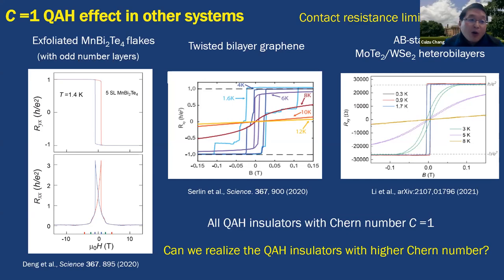In all these systems, in my opinion, it's pretty difficult to realize the room temperature quantum anomalous Hall effect, because no matter whether in ferromagnetic or twisted systems, we need the ferromagnetic Curie temperature to be around room temperature. That's pretty difficult. For example, in the magnetically doped topological insulator, if you want to increase the magnetic doping level, as I just introduced in my talk, it usually drives the magnetically doped topological insulator trivial. You will lose the quantum anomalous Hall state if you increase the magnetic doping level. In my opinion, if you want to realize a high temperature quantum anomalous Hall system, we need to find new materials. That's my opinion.